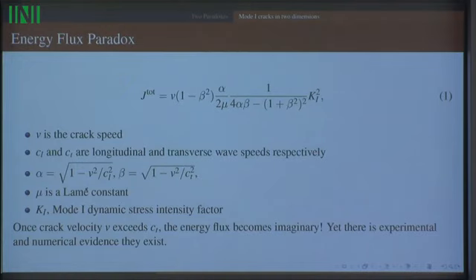One of the basic results in the continuum theory of fracture, which really started with Griffiths but then was dropped and then taken up again by Irwin and put in solid form by Rice, with beautiful contributions also from John Willis, who's in the audience, is an expression for the energy flux to the tip of a crack as a function of the speed of the crack. These quantities alpha and beta here are simply functions of the speed of the crack in relation to wave speeds, and K_I is called the stress intensity factor, and it's the coefficient of a square root that is supposed to be the universal singularity approaching any crack in the continuum.